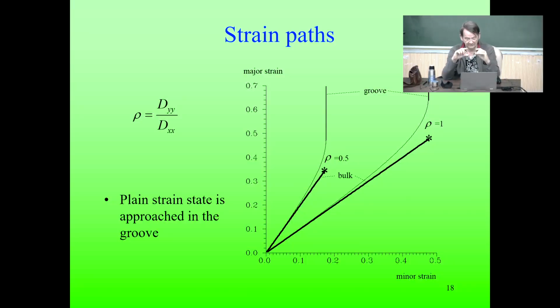The groove is decreasing its thickness. Its length is the same, but actually with the thickness also there is change in its dimension, the width dimension. That's the other component. That's plane strain. So to detect the occurrence of the instability, so at which point we have then end of formability, you look at this situation. So if it is approaching the plane strain state, so that is moving up the strain path within the groove, then there we are.